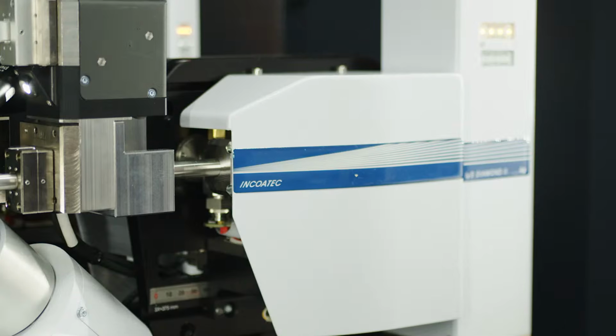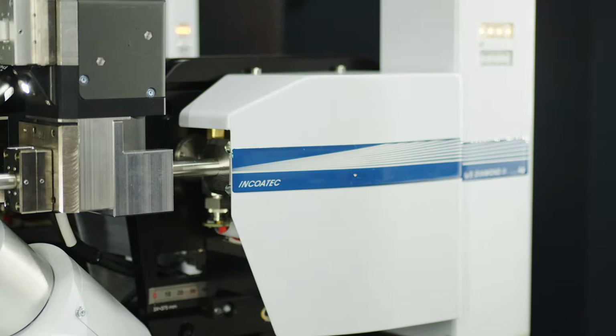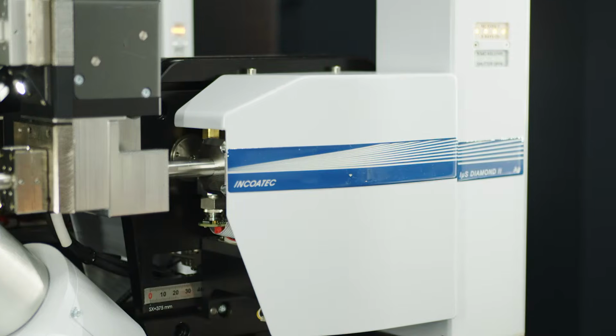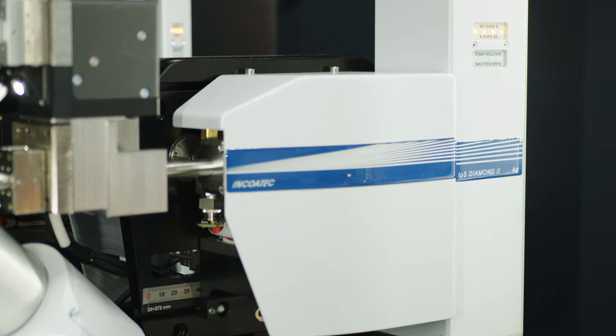So if we focus a little bit more on that source and the technological aspects, traditionally we had these sealed tubes, which were kind of large line focuses, and we could use those in points. We had some nice optics to go with them, but nowadays we're using these microfocuses, right? And that's kind of the key to a lot of this. That's really the key, especially the modern microfocus sources, the diamond microfocus sources where we have a diamond heat spreader. There's actually a reason that we call it diamond, not just some marketing term.